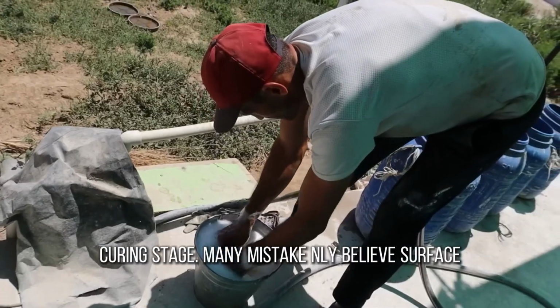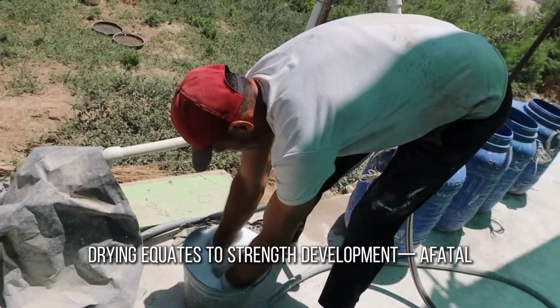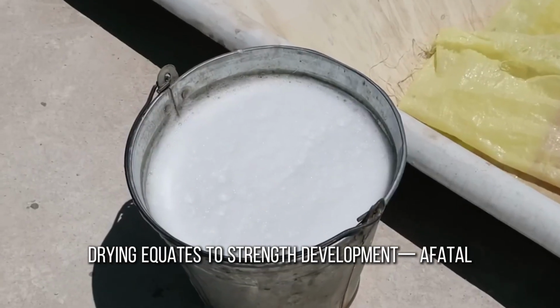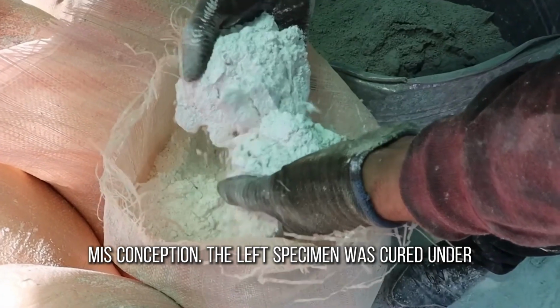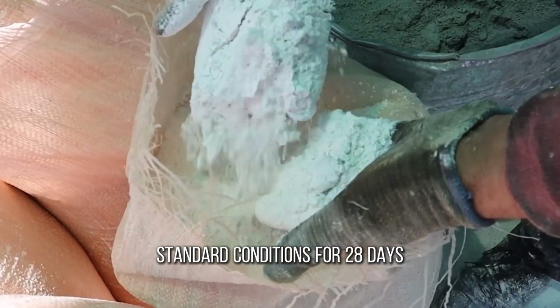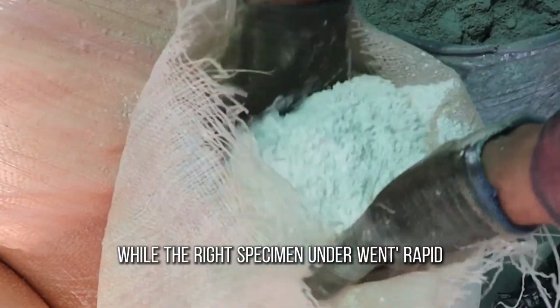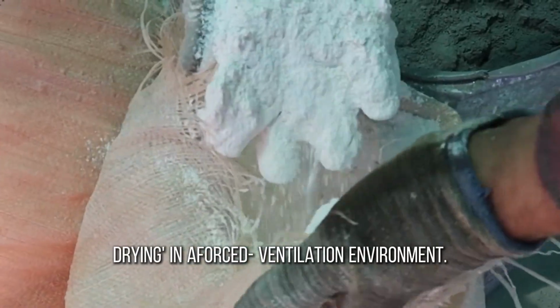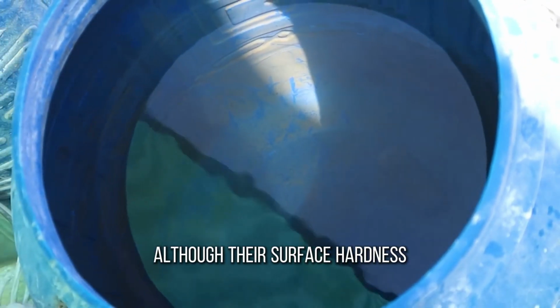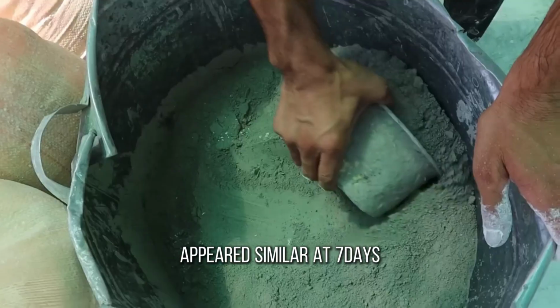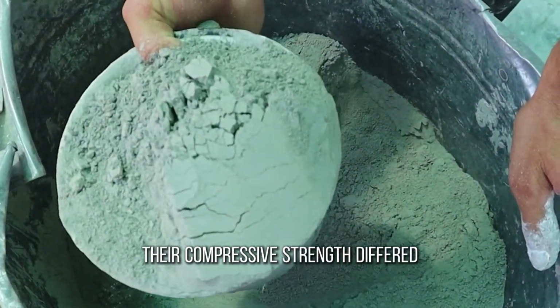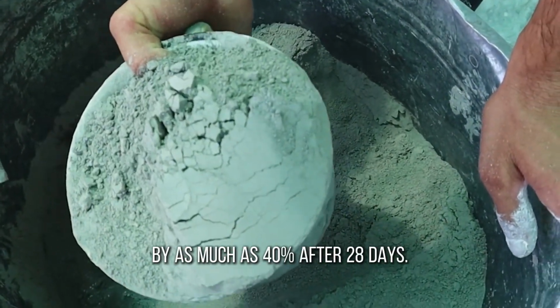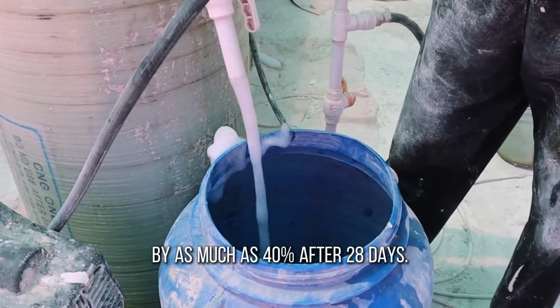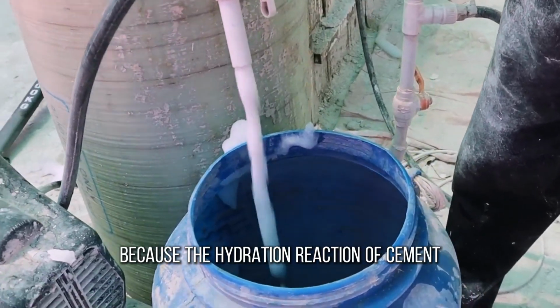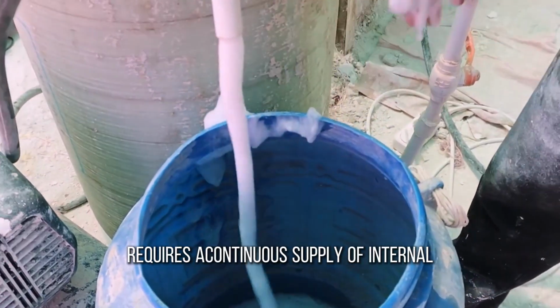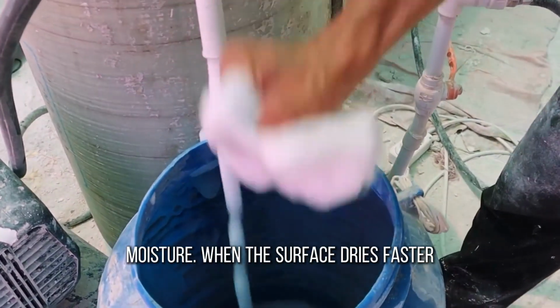The second killer lurks during the most critical curing stage. Many mistakenly believe surface drying equates to strength development. A fatal misconception. The left specimen was cured under standard conditions for 28 days, while the right specimen underwent rapid drying in a forced ventilation environment. Although their surface hardness appeared similar at 7 days, their compressive strength differed by as much as 40% after 28 days. Why? Because the hydration reaction of cement requires a continuous supply of internal moisture.